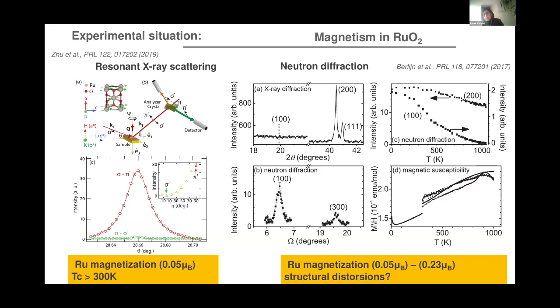When we look at the neutron diffraction data, the X-ray data don't show any peak in intensity at this 100 wave vector. However, in the neutron diffraction data, and these are the non-polarized neutron diffraction data, there is the presence of these two wave vectors, which again is compatible with having altermagnetic ordering. And this is the temperature dependence of this neutron diffraction, as well as the susceptibility, where they seem to observe something happening at this 300 Kelvin. The size of the magnetic moment that they deduce in these experiments is 0.05 mu Bohr in the case of the unpolarized neutrons, up to 0.23, but no, sorry, I think this was for the polarized neutrons and this for the unpolarized neutrons.